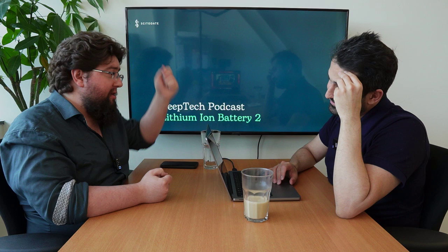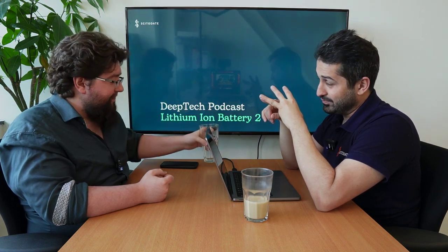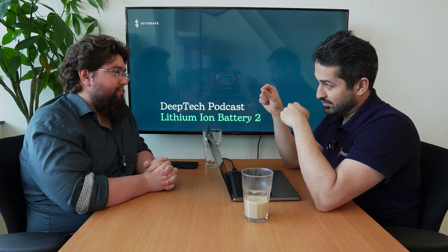So okay, and the way you trigger this is by adding and removing an electron. So you put it in an electric field, essentially, when you're charging it. Then the electron wants to, because lithium is three, it has three electrons, one more than helium. So that electron is quite loosely connected to lithium. So when it goes to oxygen, which is very hungry about electrons, the center of mass of electron and the ion, or like the nuclei, is quite separated.